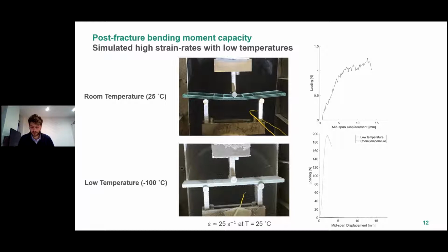A comparison of the load displacement response recorded from the low and room temperature tests indicates a significantly stiffer response at low temperatures. The results of the low temperature test demonstrate an enhancement of the ultimate load capacity of the fractured glass by 2 orders of magnitude compared to that at room temperature. This suggests an improved post-fracture bending moment capacity at low temperatures associated with the now stiffer interlayer working in tension and the glass fragments working in compression. Due to the time-temperature dependency of the PVB, a similar enhancement is therefore anticipated at the high strain rates associated with typical blast loading.